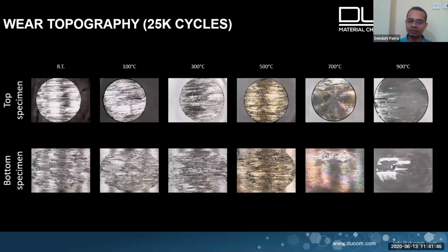So these are some of the posts. So one can also do a lot of characterization to understand material behavior. So you start observing the materials, and you see very shiny surfaces, which are typical of metallic nature. As you keep going to 900, you see the surfaces have become dark. After rubbing, the surfaces have become dark.